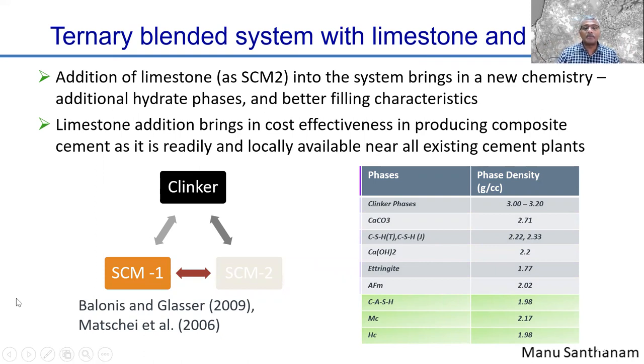You have monocarbonate, hemicarbonate, and in the long term, the supplementary material 1, that is fly ash or slag or calcined clay, undergoes pozzolanic reaction to produce what we call calcium aluminosilicate hydrate. So now you've replaced cement partially with a combination of limestone and supplementary material. The kind of reactions and the chemistry that you get in the system leads to the formation of a greater amount of solid hydration products. You know very well in concrete, the more solid hydration products that you form, the less porosity that you get. The less porosity that you get, the higher your strength goes.